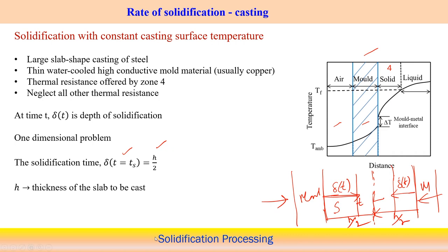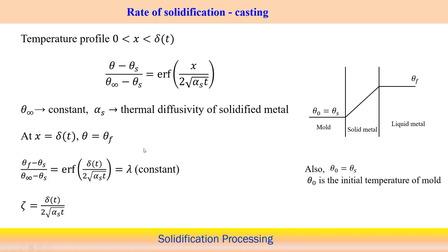So, in this situation, how to analyze the other cases? We can do a heat transfer analysis. Here you can see the temperature profile looks something like this. This is the mold surface, the mold and metal surface, this is the cast column on the right hand side, and this is the mold component. Now there is a depth of solidification at a particular time, suppose delta, as a function of t, delta t, and at this point the temperature will be theta f, the freezing temperature. Here also we are neglecting the superheat temperature.